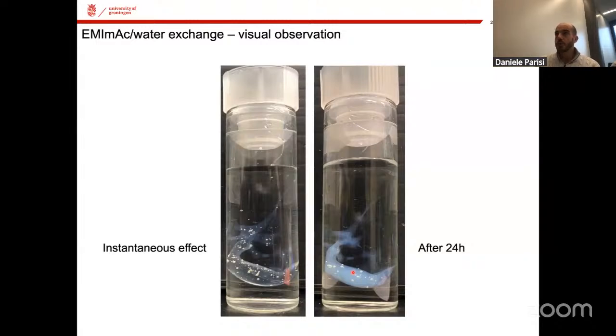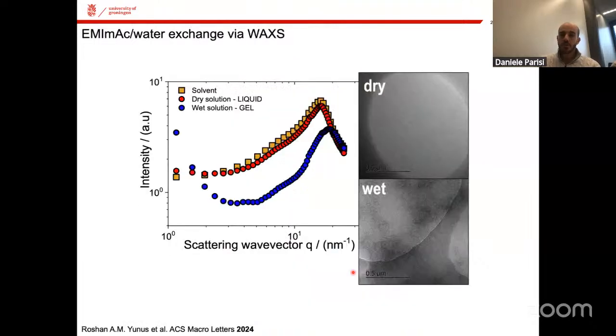So there was a question here: are we forming any crystalline domains? So for this reason, we ran some wide angle X-rays, and everything looked pretty much isotropic. So we couldn't, let's say, detect any Bragg peaks. So it really looks like either microphase separation or the formation of very big clusters among cellulose chains.